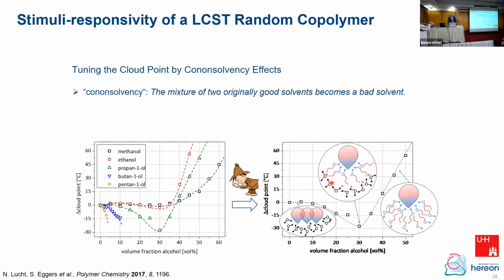And then you see the alcohols, in this case propanol, which with the OH group interacts with the hydrophilic part of the polymer, and the hydrophobic part is towards the water, which is not good. At a certain concentration of alcohol, this type of association seems to be dominant, and that gives you the minimum in the cloud point. Now, when you increase the amount of alcohol, there is so much alcohol that it can maybe form a double layer. That is what you see here. So again, a hydrophilic group is towards the outside.